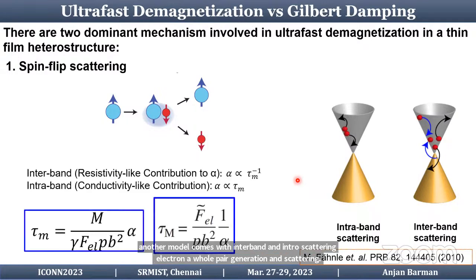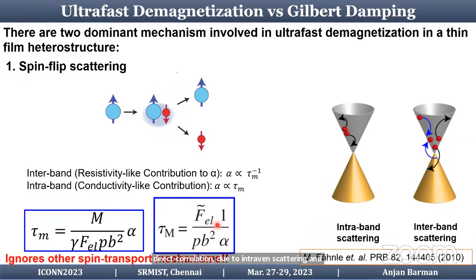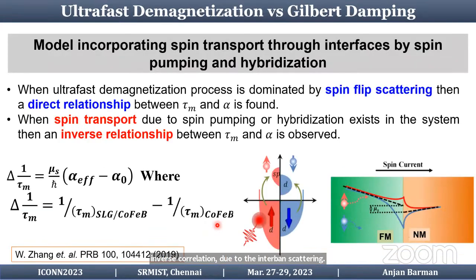But that also gives rise to two different dependences, like direct correlation due to intraband scattering and inverse correlation due to the interband scattering, but that ignores the spin transport mechanism. So more recently in 2019, Zhang et al. gave rise to another model by incorporating the spin transport model, which shows that this inverse correlation is actually due to the spin transport, where they have a dependence like that, whereas the direct correlation corresponds to the spin flip scattering.